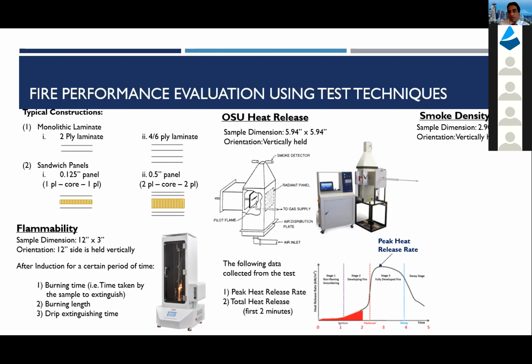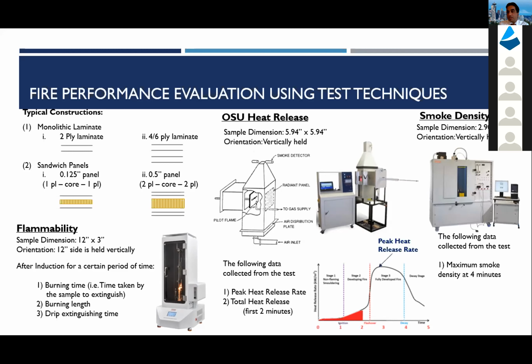Then the smoke density test. In the smoke density test, sample coupons are 2.9 inch by 2.9 inch. Samples are held vertically. And here is a picture of a smoke chamber. The information we collect from this test is the optical density of smoke at 4 minutes after inserting the sample.